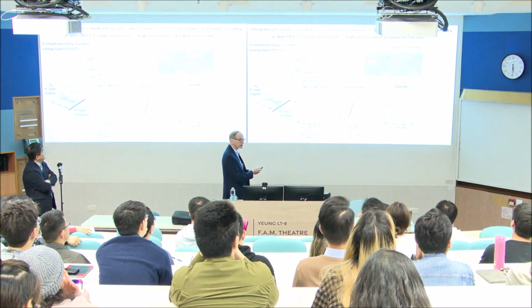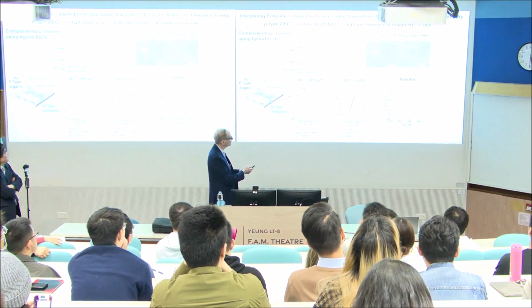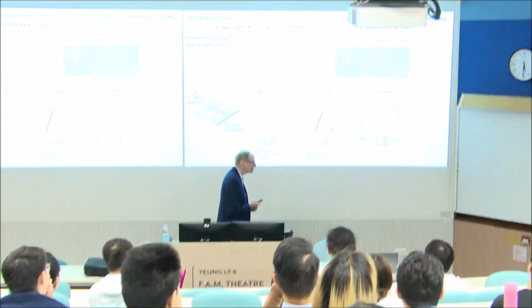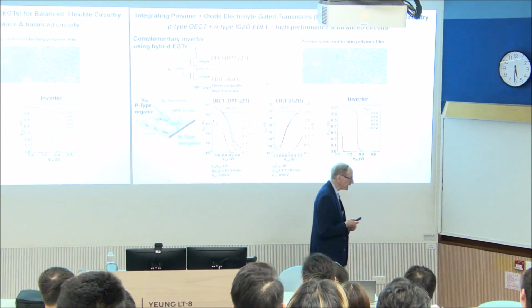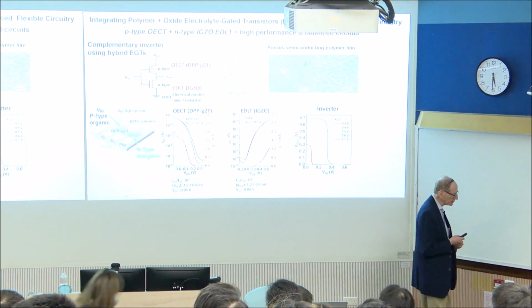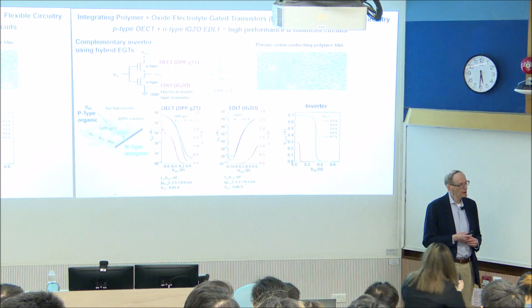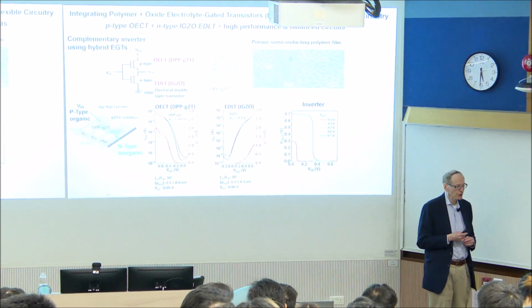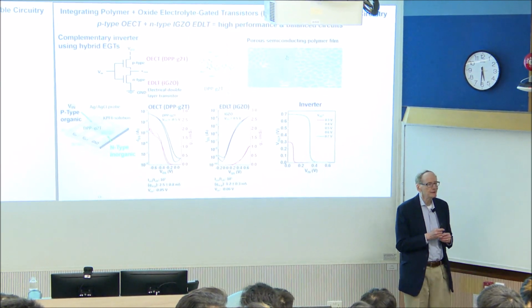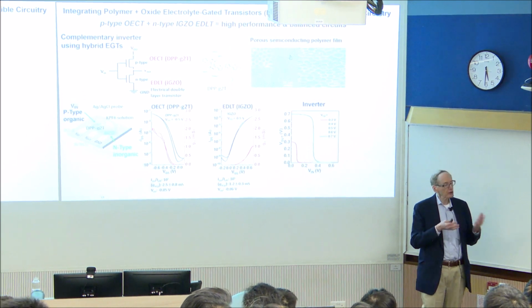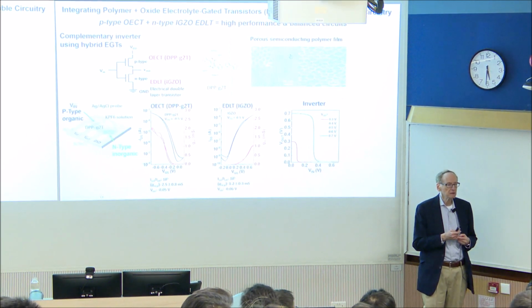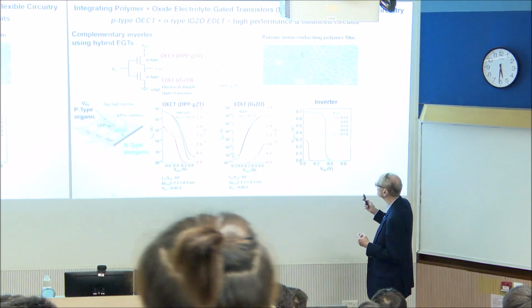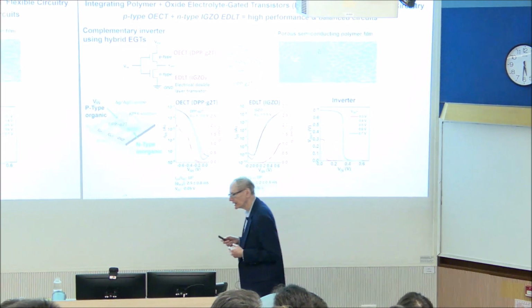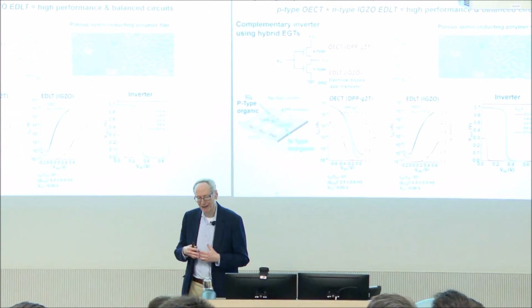So you can see, obviously, you've got much less semiconductor here, and they have to obviously go around these pathways. So the mobility does go down some. But on the other hand, when it's an electrochemical transistor, you get these enormous transconductances. I think we're okay now. So it's a trade-off. But because these are mostly amorphous, it's not as if you're interfering with the packing.